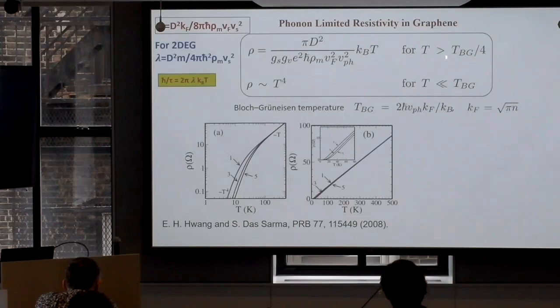But this high temperature is not the Debye temperature. Often people in books say Debye temperature. It's either the Debye temperature or the Bloch-Gruneisen temperature, whichever is smaller. And in metals, the Debye temperature is much smaller than the Bloch-Gruneisen temperature because the Fermi momentum is so high. But in graphene, it's really the Bloch-Gruneisen temperature.